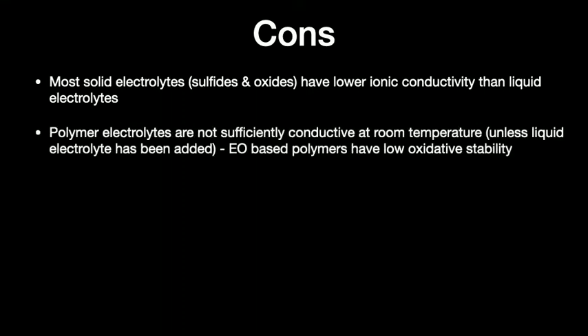Cons. Most solid electrolytes, sulfides and oxides, have lower ionic conductivity than liquid electrolytes. Not always true, but quite often that is the case. Polymer electrolytes are not sufficiently conductive at room temperature. So most solid state batteries using polymer electrolytes have to be operated at high temperature, maybe 80 centigrade, unless you add liquid.